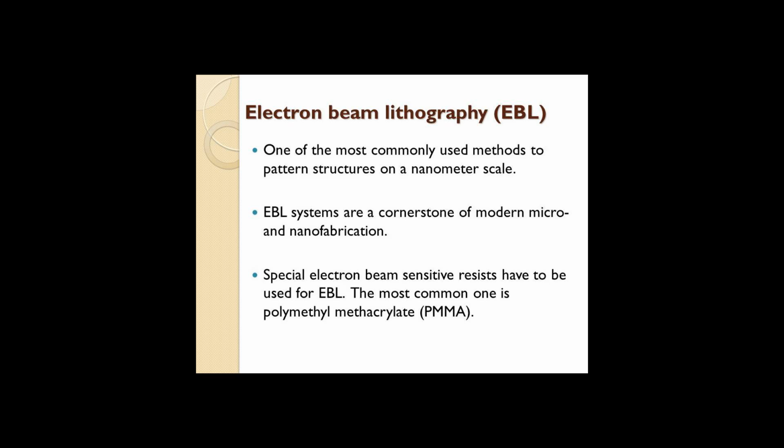For example, assuming an exposure area of 1 square centimeter, a dose of 10⁻³ coulombs per square centimeter, and a beam current of 10⁻⁹ amperes, the resulting minimum write time would be 10⁶ seconds, about 12 days. This minimum write time does not include time for the stage to move back and forth, as well as time for the beam to be blocked from the wafer during deflection, as well as time for other possible beam corrections and adjustments in the middle of writing.